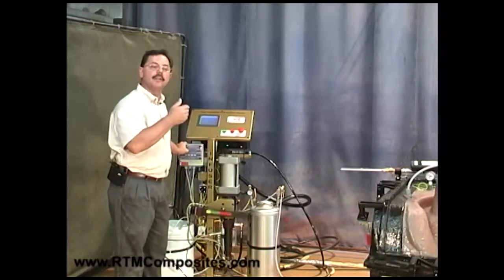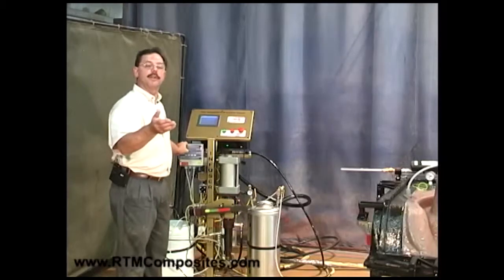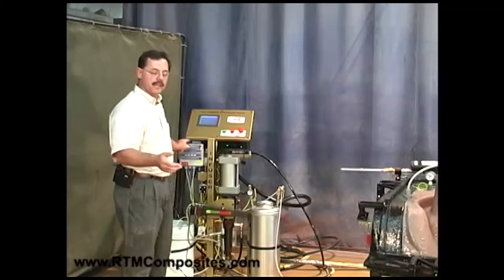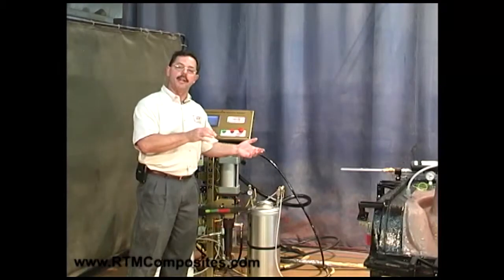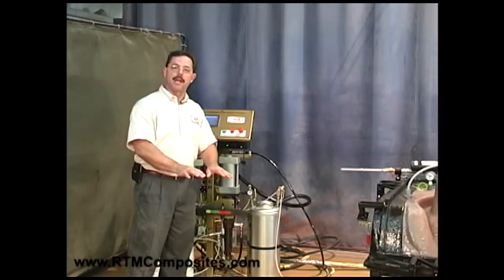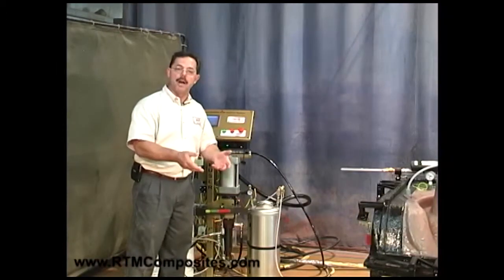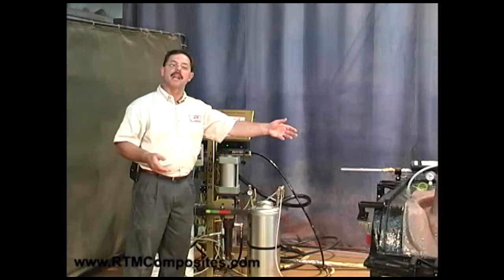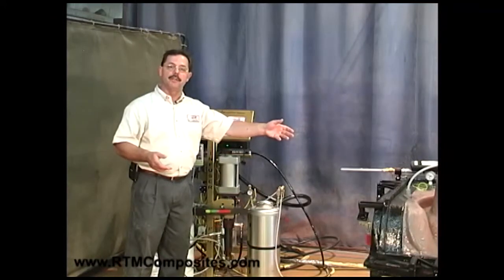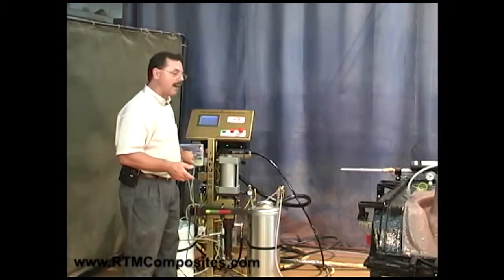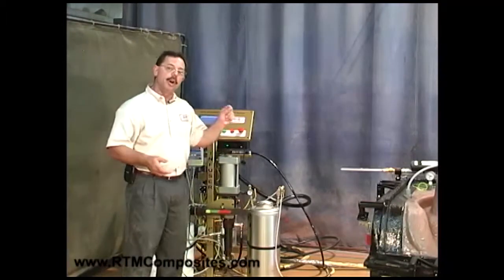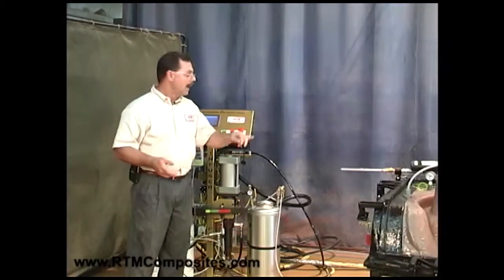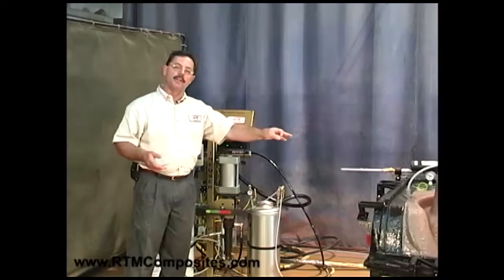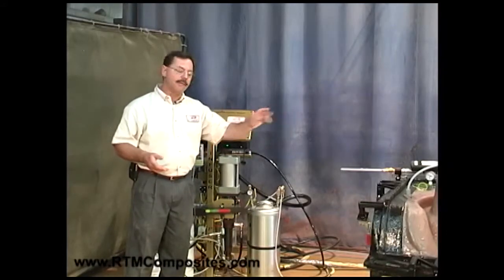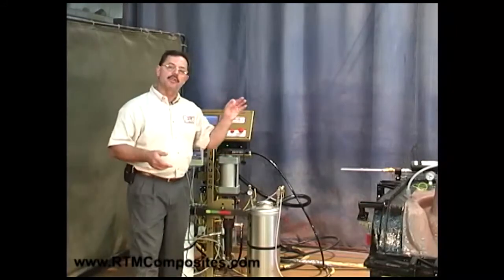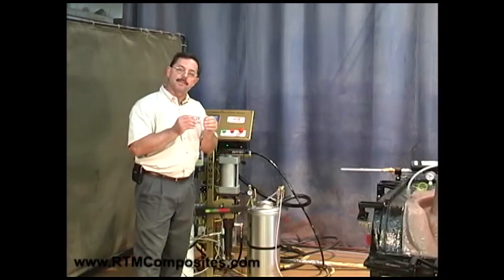Again, operators over the years, we have seen it countless times. Either they didn't put the right amount of filler in or let all the filler settle to the bottom of the tank. So now he's pumping mud. And the symptom is there are problems in the repeatability of the injection. Well, if we set parameters around the specific gravity, we know that the filler load is constant. We then say, well, we want the resin to go in at the same temperature constantly. We have that. Now we say, all right, I want to inject it, but I want to inject at a specific rate.